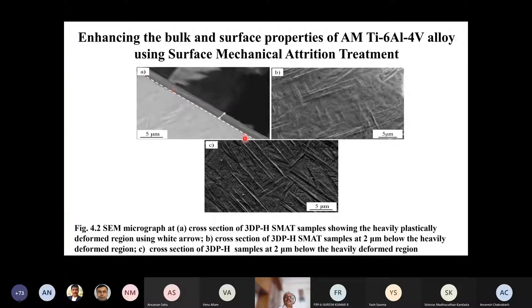One was the surface mechanical attrition treatment, which is a modified version of the traditional shot peening process. There, without making significant change in the dimensions of the component, we hit the surface with very small balls at a controlled frequency, and we try to nanocrystallize it. It has many positive effects. One is it introduces compressive residual stresses. As I mentioned, residual stresses are inevitable in the process, so residual stresses are generated. And we also know that if the residual stresses are compressive in nature, it adds to enhanced fatigue life of the material.